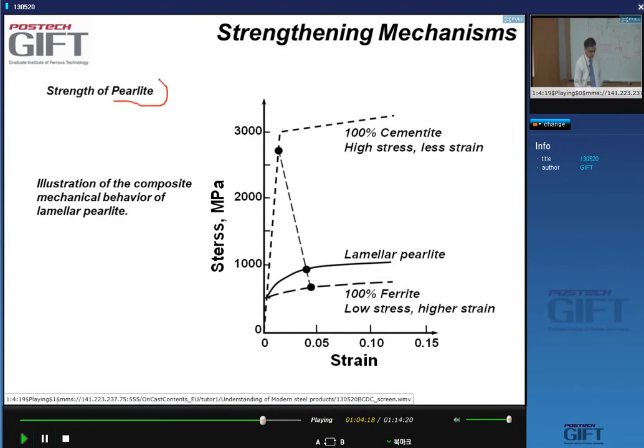Now, the pearlite itself, what is the pearlite? The pearlite is a composite material. Cementite has an extremely high strength, in fact extremely high yield strength, close to probably 3,000 megapascal, whereas the ferrite that surrounds it is a much lower strength material. So these would be, in comparison, the stress-strain curves for your cementite and your ferrite. The stress-strain curve of your lamellar pearlite is somewhere in between.